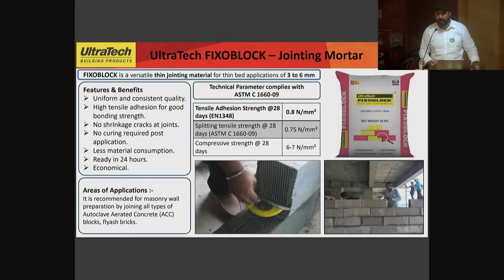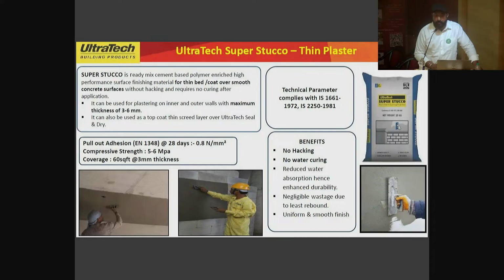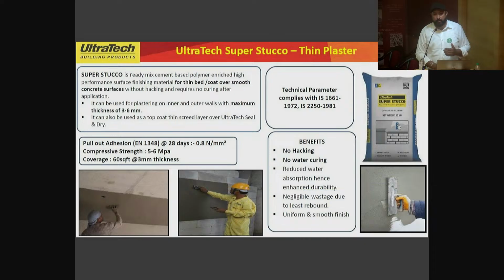This is a Fixoblock, a jointing mortar with which we can fix the blocks. The compressive strength of this product is around 6 to 7 Newton per mm square. This is the super stucco. No curing is required. You just have to mix water, 25% by weight, and you can apply it as a putty. You get a 3 mm plaster, but you have to apply it on blocks or on a concrete surface. So it is a very thin layer plaster and no curing is required. Rest all the products you have to cure at least 2 to 3 days, 2 to 3 times a day.